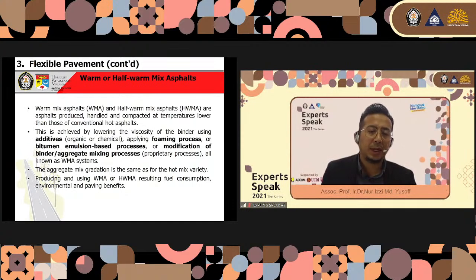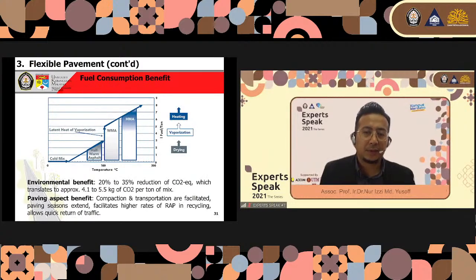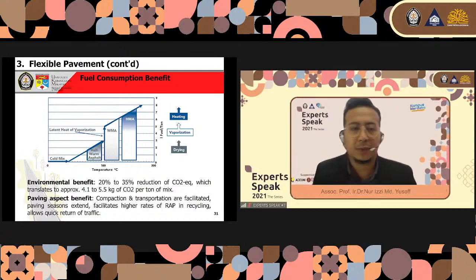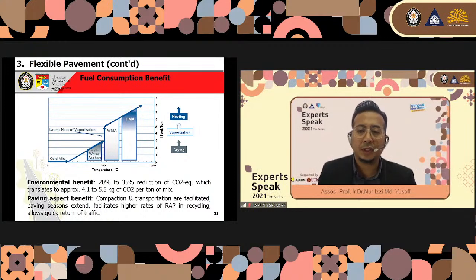Producing and using WMA or HWMA results in fuel consumption, environmental and paving benefits. This is what we try to achieve when we use WMA technology. The first one, of course, we try to get the benefit from the fuel consumption, and you can see this from the figure. It shows how HMA and WMA fit into the full range of techniques from cold mix to hot mix, and the approximate fuel usage per type of mix. And then in terms of the environmental benefit, there is a 20 to 35% reduction of carbon dioxide equivalent, which translates to approximately 4.1 to 5.5 kilograms of carbon dioxide per ton of mix.